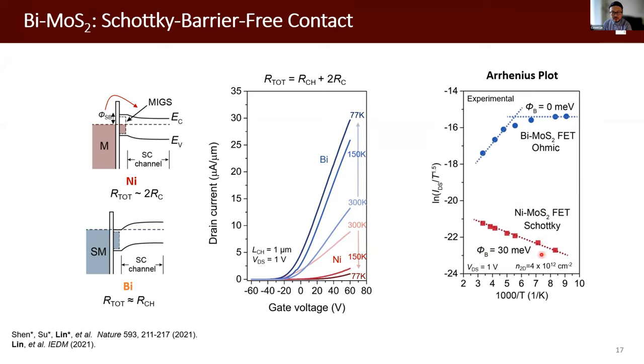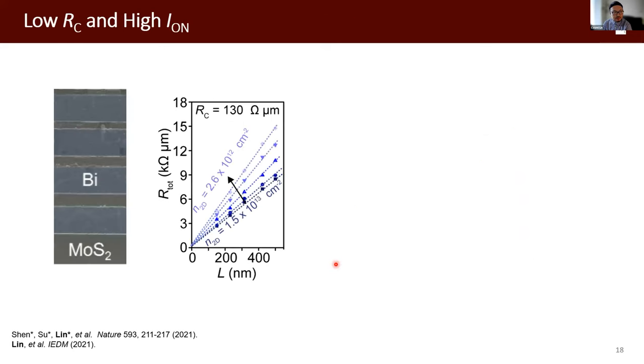And from the negative slope, we can extract the barrier height at the contact. So for nickel contact transistor, the barrier height is around 30 milli-electron volts when the device is completely turned on. But for the bismuth contact devices, the trend is opposite. That means there isn't any energy barrier at the contacts, and this negative trend is dominated by the carrier transport within the channel of the MoS2.